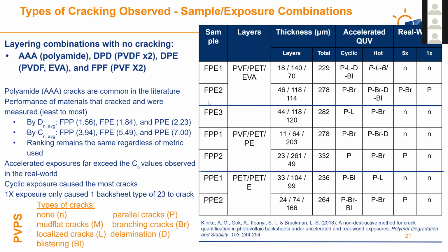And what we also found is we got a lot more cracking when we had the cyclic exposure that caused the most cracks. So again, as Gernot was saying, we were incorporating UV plus a thermal shock with going to condensing humidity and changing temperatures.